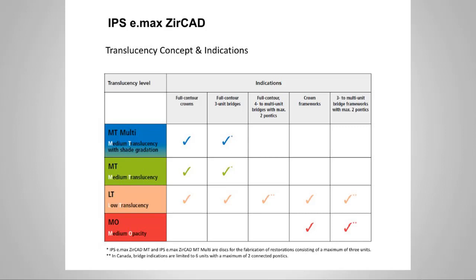So looking at how those 4 pucks can be used, you can see the different indications. The MT multi: full contour crowns and full contour 3-unit bridges. You can see that the stronger zirconias, the lower translucency and the medium opacity, are used for a lot of different things. The LT is probably the workhorse, and you can see that it has indications of use for almost every category.